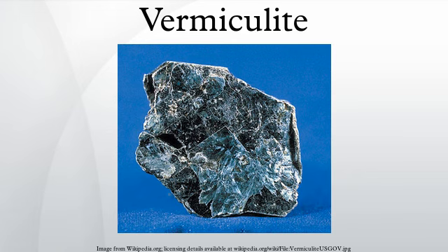Structure: vermiculite is a 2:1 clay, meaning it has 2 tetrahedral sheets for every 1 octahedral sheet. It is a limited expansion clay with a medium shrink-swell capacity. Vermiculite has a high cation exchange capacity at 100 to 150 meq/100 g. Vermiculite clays are weathered micas in which the potassium ions between the molecular sheets are replaced by magnesium and iron ions.